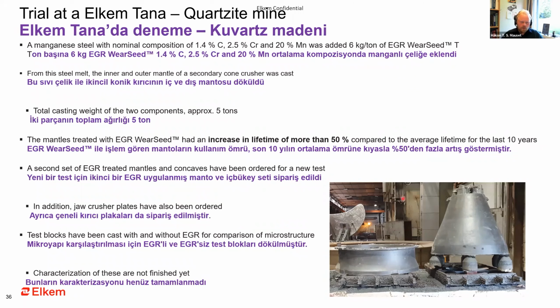So then we chose to make a manganese steel of 1.4% carbon, 2.5% chromium, and 20% manganese. And then we added 6 kilograms per ton of steel. We added EGR wear seed. And from this steel melt, we made the inner and the outer mantle of the secondary cone crusher at Elkem Tana. The total casting weight of these two components was approximately 5 tons.